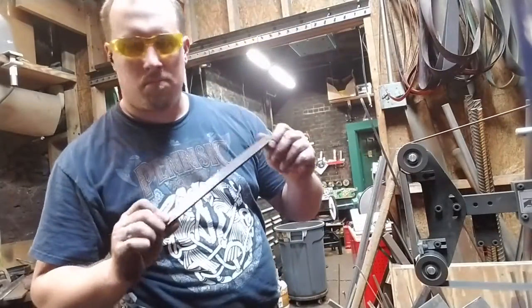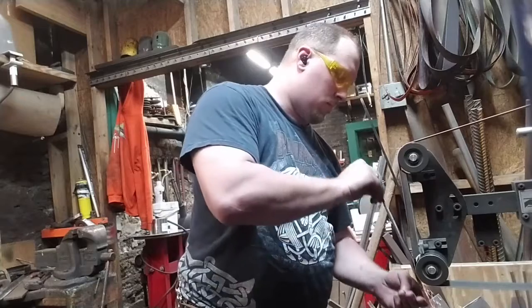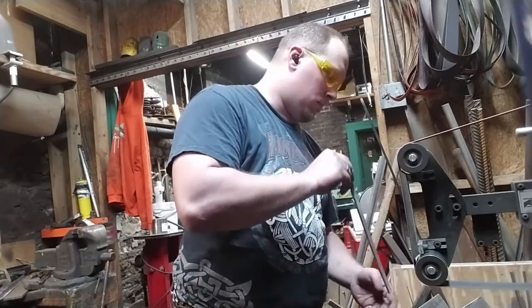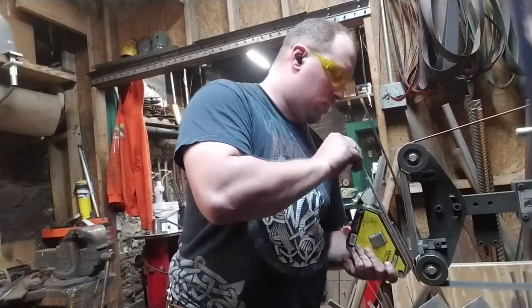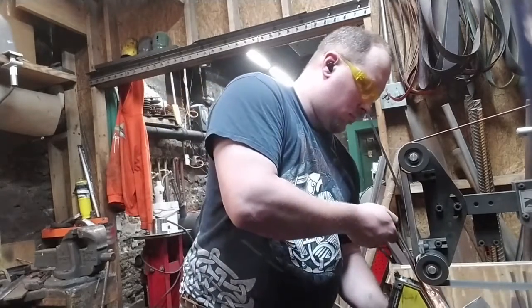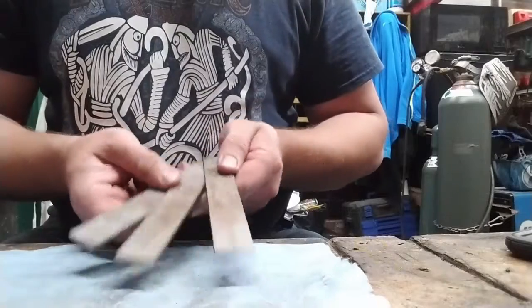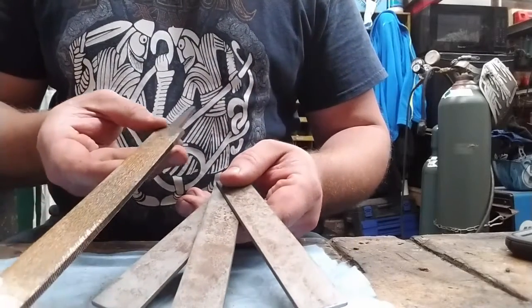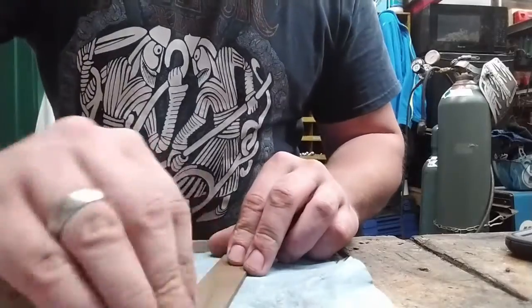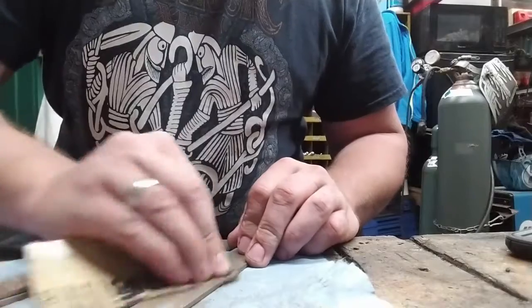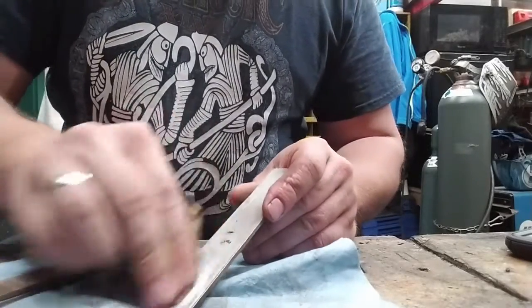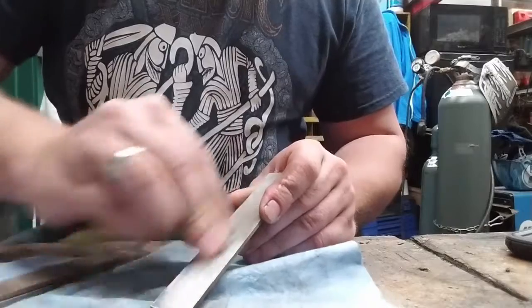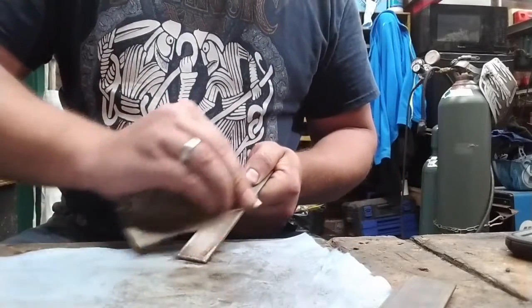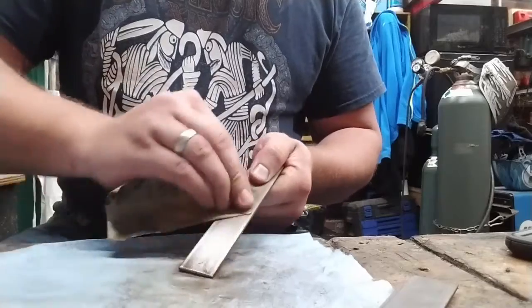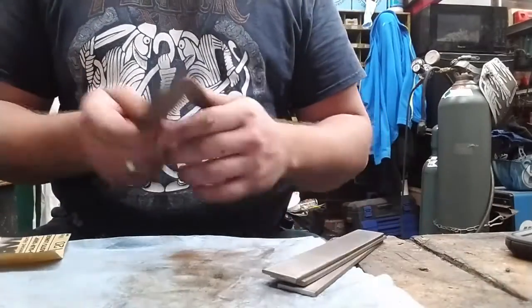And right now we're going back to the file that we started with and set aside. Since we've taken the trouble to remove its heat treating, it's very much easier to grind down to flat. You don't have to flatten something like a file, but you risk cold shuts if you don't. So now we're on to making the blade steel portion of the knife. And again, this is some of the steel that we went through the cementation process with, the steel that we made into high carbon steel.